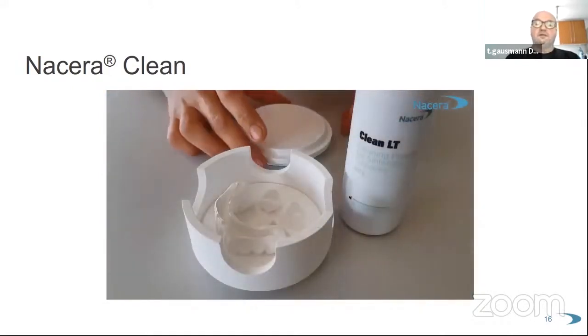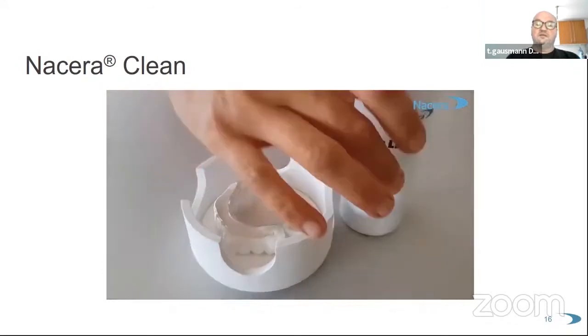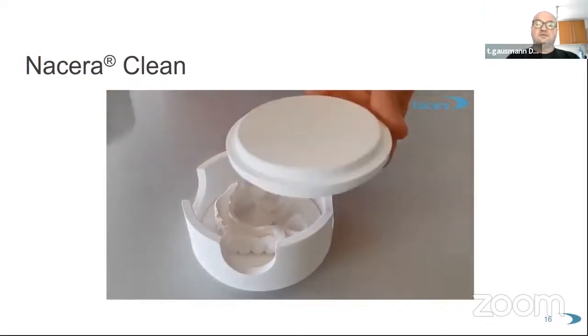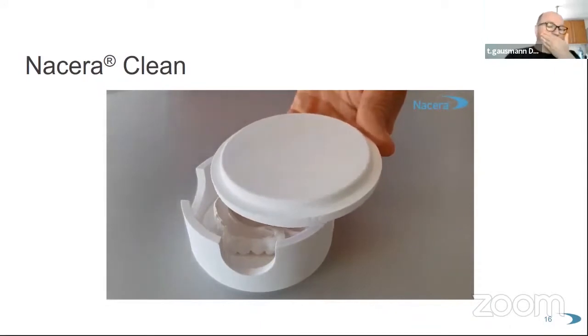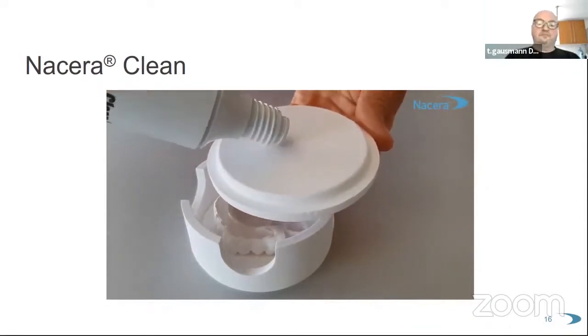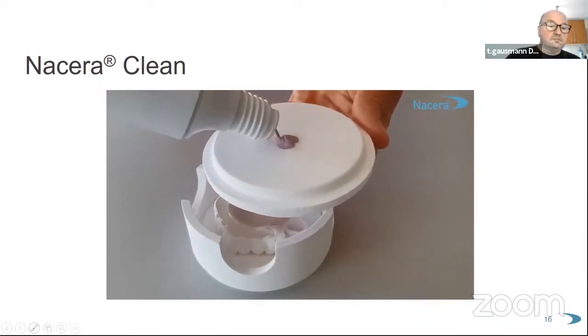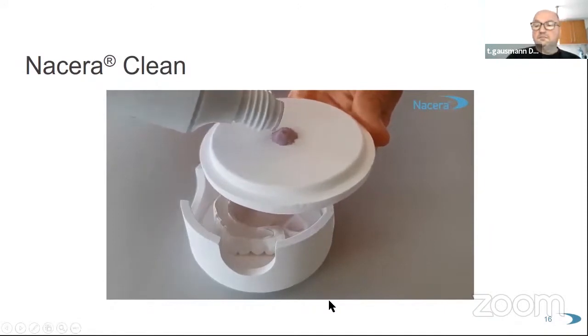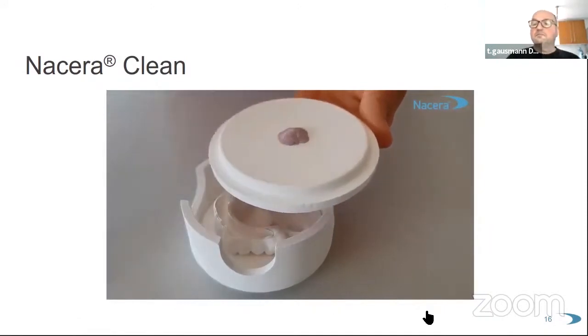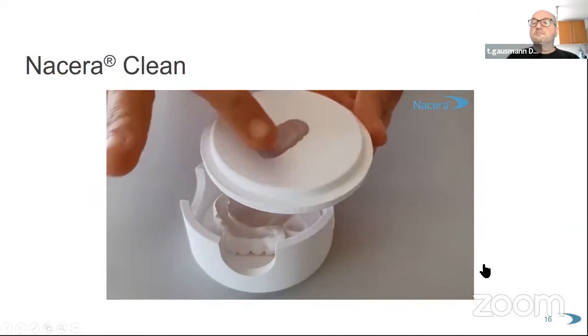For a maintenance cleaning, or to avoid your sintering furnace to be polluted, use Clean LT in each sintering process. Put a small amount of the powder on the lid and spread it to increase the reactive surface on which the impurities can settle.